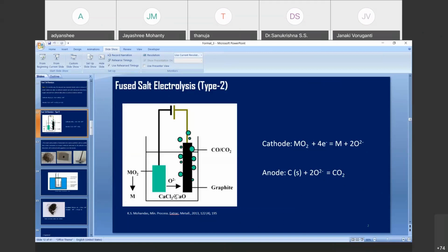So in this process, you have to apply a potential that is sufficient for the decomposition of CaO. At this potential, as soon as the CaO is formed, it is decomposed, and the oxide reacts with the carbon to produce CO or CO2, depending upon the potential. This is the basic mechanism.